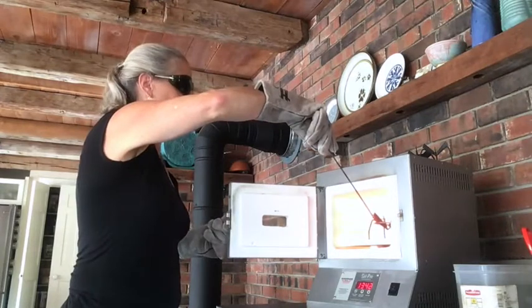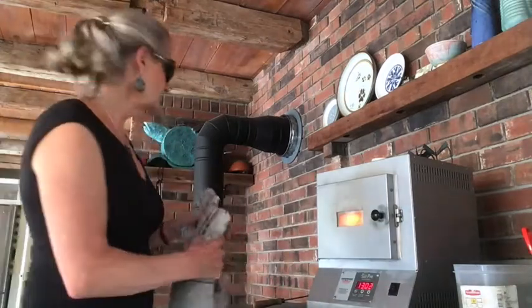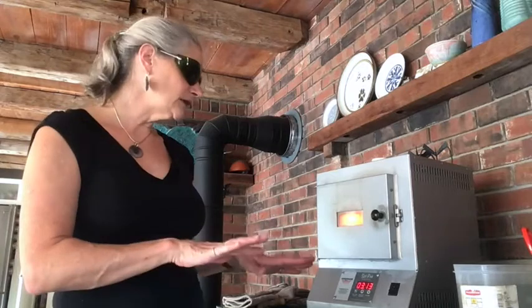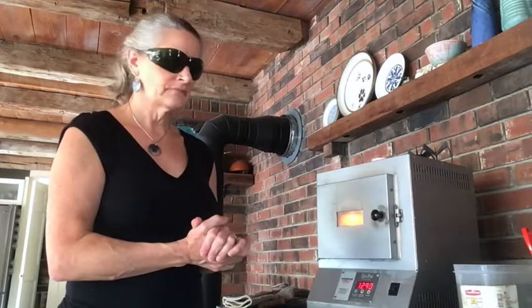It's going to go all the way up to temperature. It's going to melt the enamel enough that the image can fire in. You don't want to keep it in there too long, because if it begins to settle into the liquid glass, then the image will dissipate a little bit and it won't be quite as crisp. So it needs to come out pretty close to when it just reaches temperature. I like it to get fired in, but not too comfortable, not floating down into the enamel.